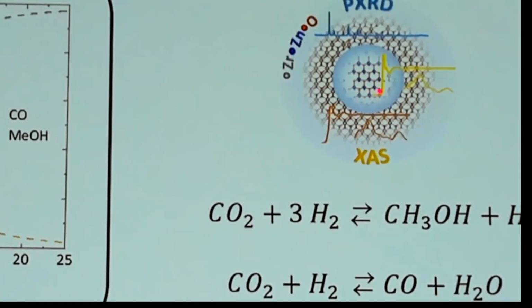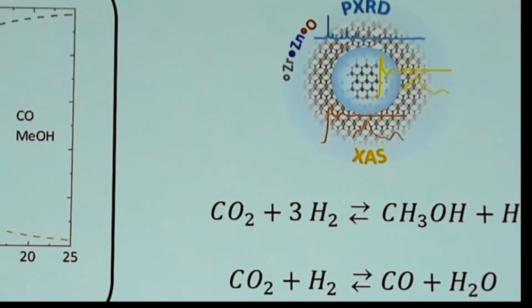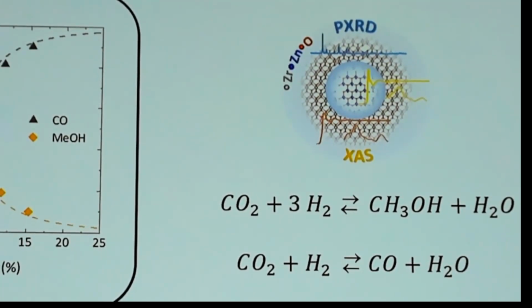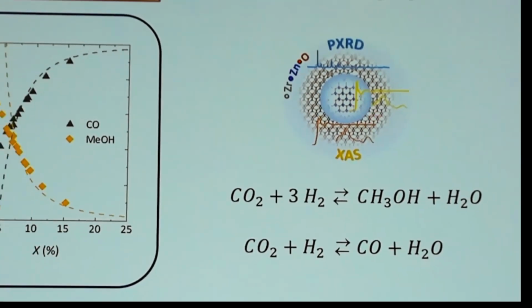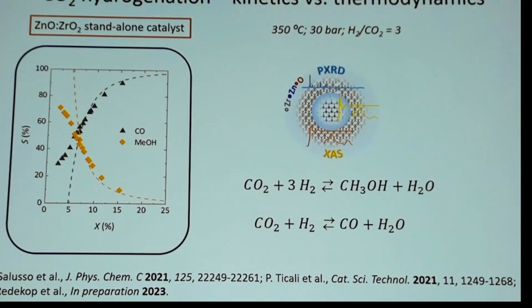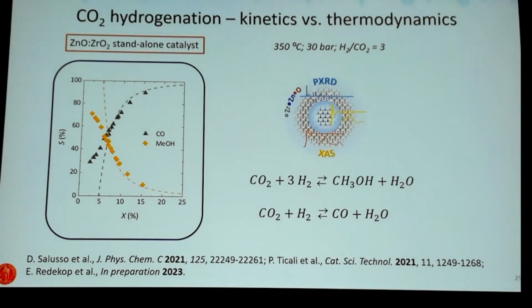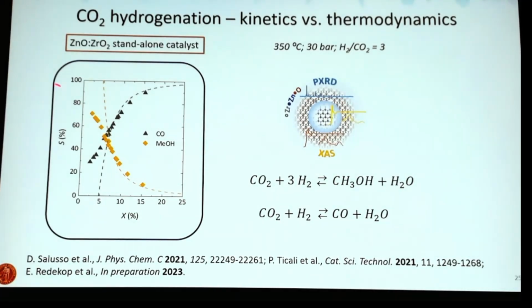And so under the reducing conditions that we have under CO2 hydrogenation, the zinc oxide is depleted in oxygen, and we have a heterolytic cleavage of hydrogen on the zinc oxide. Then CO2 is adsorbed on the zirconia cluster, and they react at the interface. Theory predictions say that methanol is the preferred product, and this is what we see also experimentally when we test.